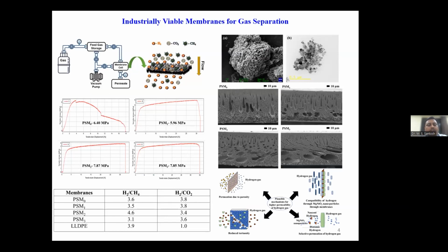So in the simulated environment, we place the flat sheet membrane in a membrane cell and feed the gas. As the gaseous mixture passes through the membrane, it separates out only hydrogen and offers it as a permeate. These hydrogen molecules effectively permeate through the small pores available on the surface, and separate hydrogen from the rest of the gaseous mixture under a certain vacuum environment. When we tested this membrane, these membranes are typically mixed matrix membranes, which comprise nanoparticles as well as polymer materials. The combination of the polymer and the nanoparticle effectively brings the hydrogen separation efficiency to a